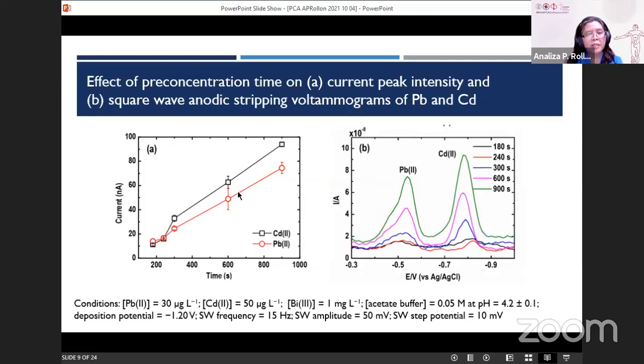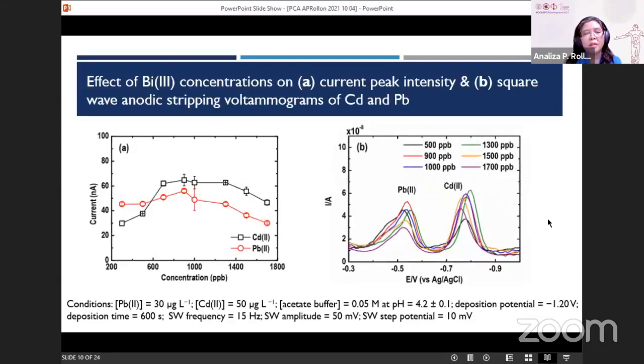So actually, if you can see in here, even at 600 seconds, that must be enough, because even beyond that, we still have a linear relationship. We don't want to be working on a range wherein it's already becoming nonlinear. And for the effect of the bismuth concentration, these are the voltammograms.